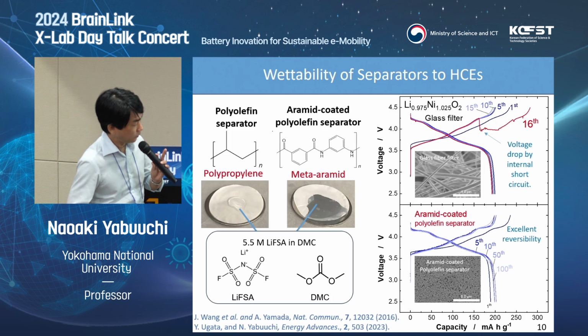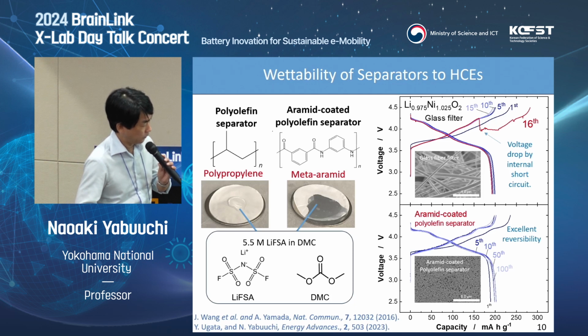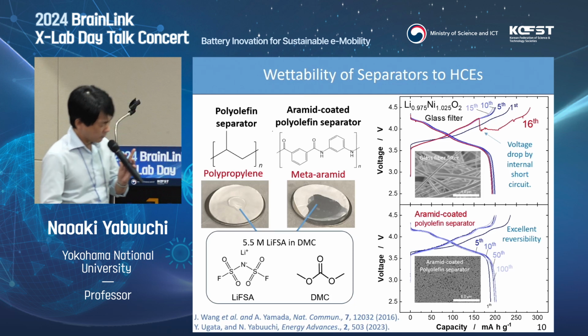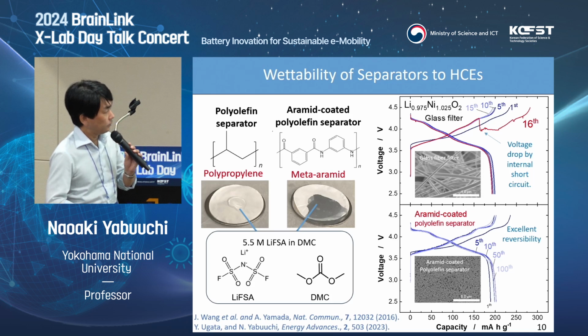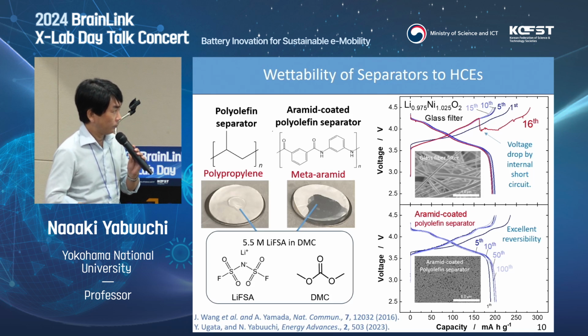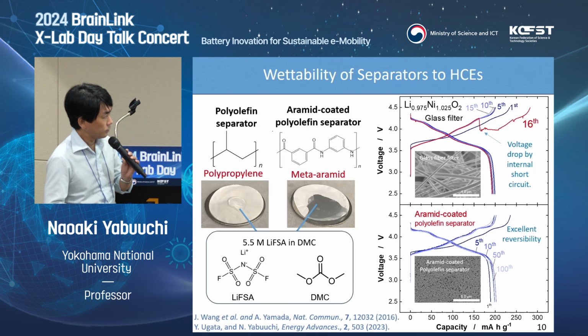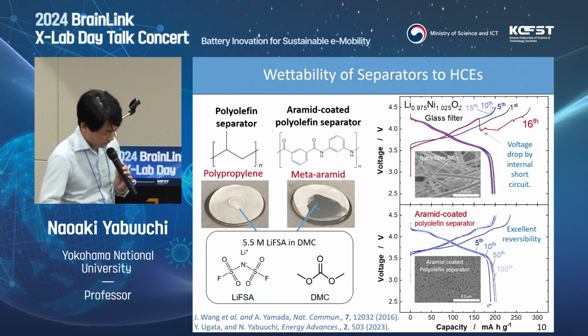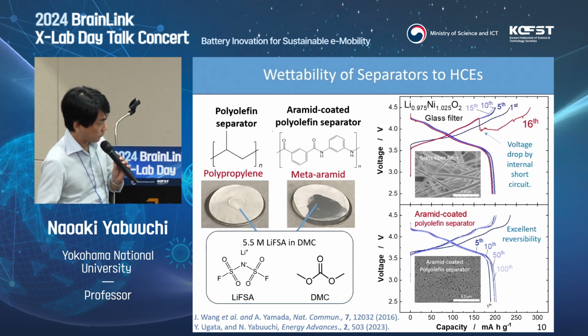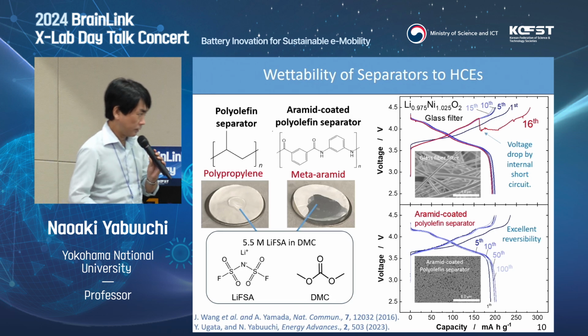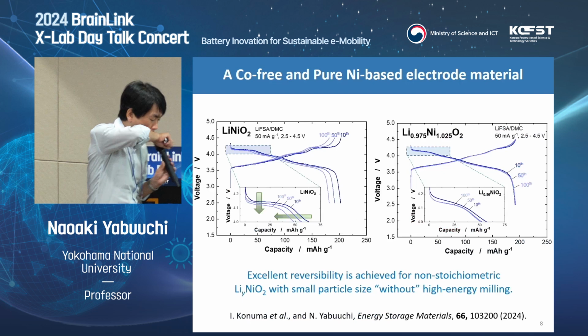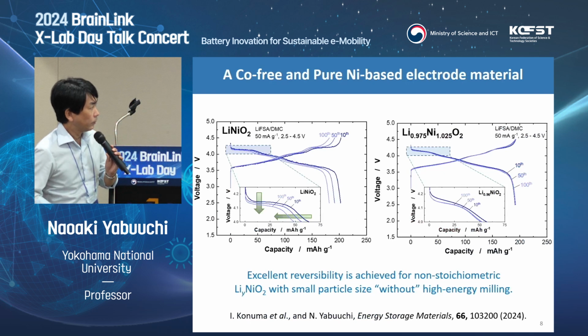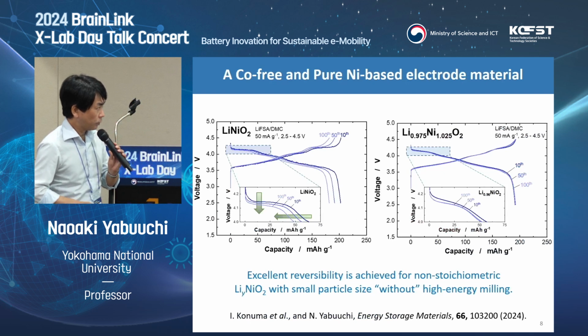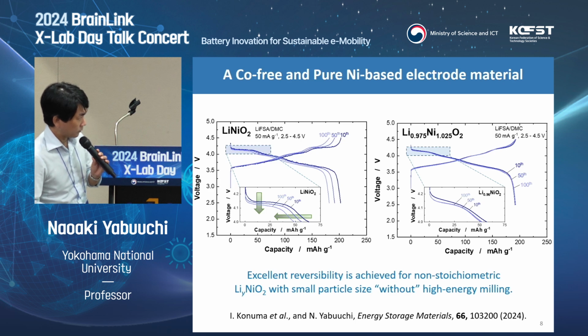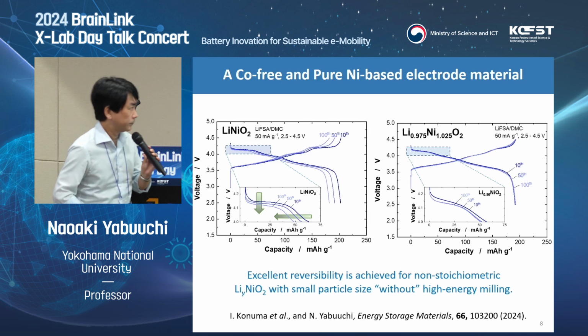Polyolefin separator shows very small porosities, small pores. However, aramid has oxygen functional groups. So this oxygen presence nicely improves wettability to highly concentrated electrolyte solution with high viscosity. As a result, reversibility is clearly improved. Reversibility for the non-stoichiometric lithium nickel oxide sample with highly concentrated electrolyte solution is also clearly improved.